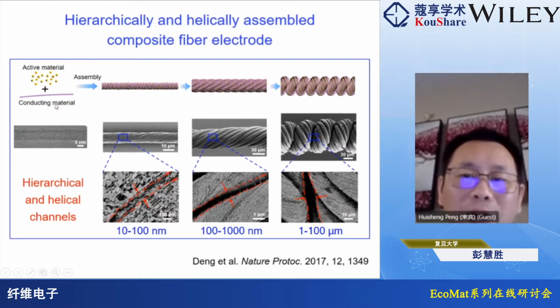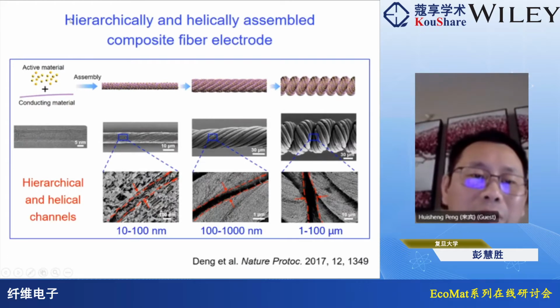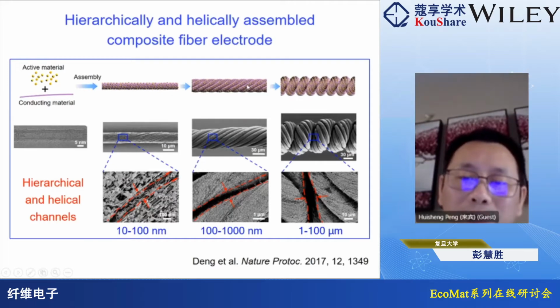Here is just one example. We use what is called hierarchical and helical assembly to make this composite fiber electrode. Here's one case: for example, carbon nanotubes can be twisted with the active material to form a first-level fiber, and then the first-level fibers can be twisted into larger fibers, and even much larger spring-like fibers.